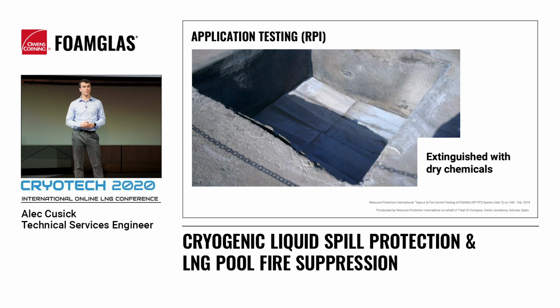One additional benefit that we like to mention around this PFS Gen 2 system is the fact that upon conclusion of the second round of testing, someone was able to approach the pit wearing proper PPE and actually extinguish the flames using nothing but dry chemicals. This is not something that would traditionally be possible in the same containment pit when no suppression system is installed.